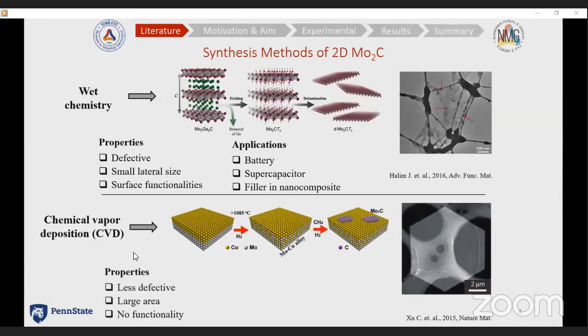And if you introduce a carbon precursor such as methane gas, then you can form 2D molybdenum carbide on the copper surface. And as is seen from the TEM image here on the right-hand side, it is much less defective than the one synthesized by the wet chemistry method, and it is a large area. And also, since there is no acid treatment or wet chemistry, there is no surface functionality on its surface. So therefore, it can be used in electronic and magnetic applications, and also it's a good platform to examine the intrinsic properties of 2D molybdenum carbide.